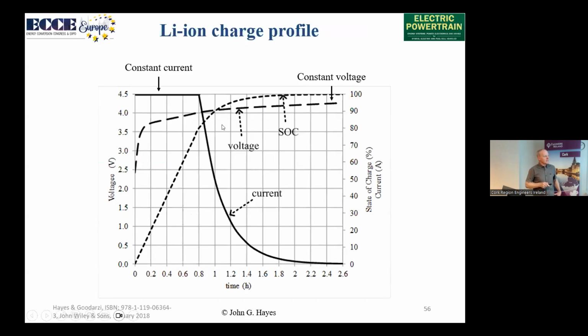So that's the dashed line here. When we're fully discharged, we have a 0% state of charge. We're going to start pumping in the solid line as the current. We'll start pumping in full current, and we see the state of charge is going to rise. The voltage of the pack, or the battery, is going to rise to about 4.2 volts.